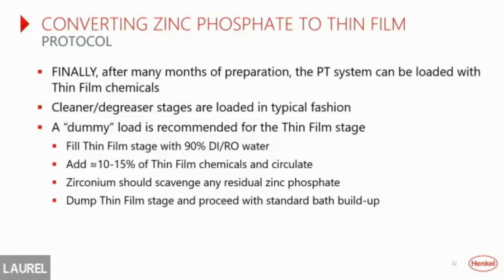And then circulate. What that zirconium will do is, if there's any residual phosphate roaming around in there that is loose, it will scavenge it. It'll bind to it, or the phosphate will bind to that. Dump it, hose down the walls, fill it up with water, and then build up our bath.